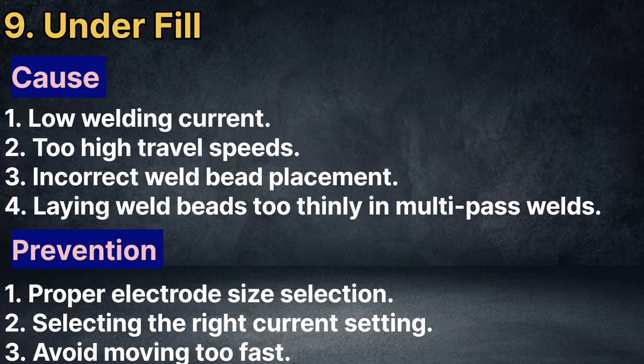The underfill causes: first low welding current, second too high travel speeds, third incorrect weld bead placement, and last one is laying weld beads too thinly in multi-pass welds. For prevention, we have to follow proper electrode size selection, select the right current settings, and avoid moving too fast.